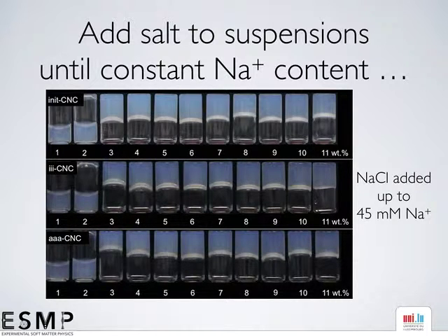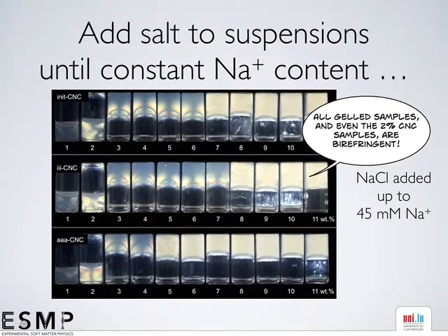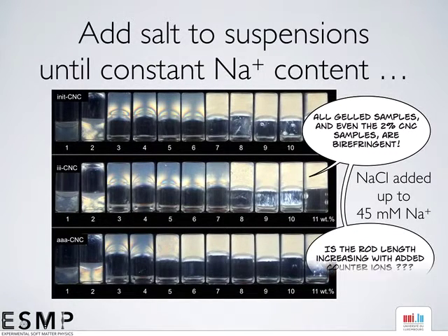So in fact, it seems by tuning the counterion concentration, we can really control gelation. And moreover, if you look at the samples between cross-polarizers, the previous ones were without polarizers, then you can also see where something forms a liquid crystal. And that surprised us as well, because they all are liquid crystalline. Even the 2% sample that is not gelled forms a liquid crystal. So that suggests to us that somehow the effective rod length seems to be increasing by adding counterions. And the question is, of course, how?